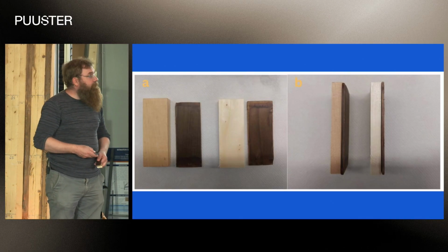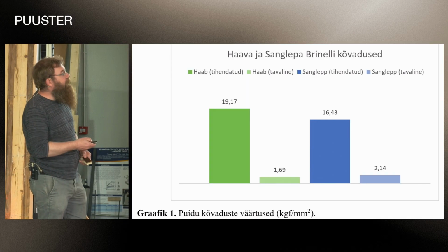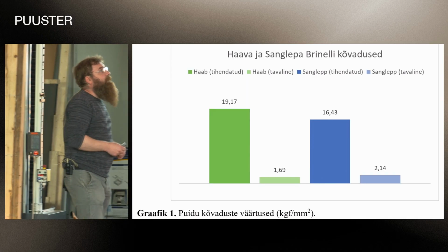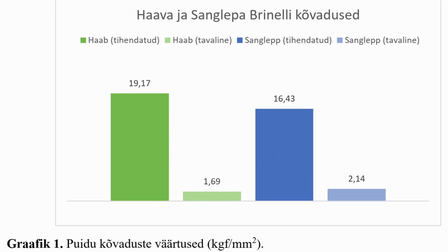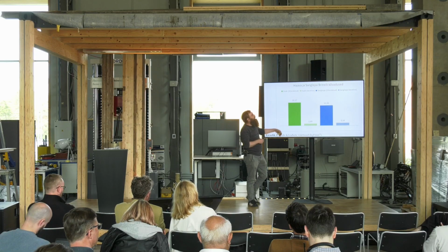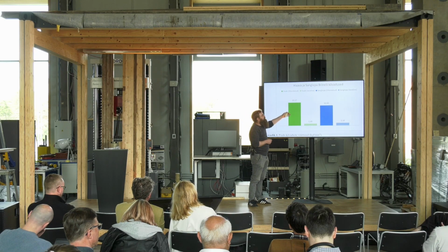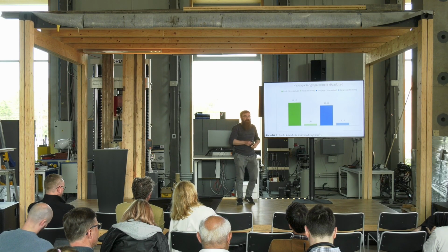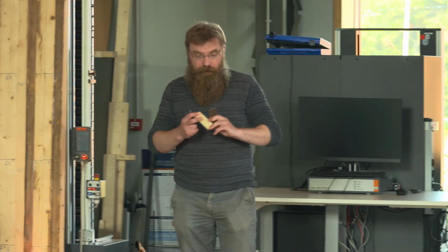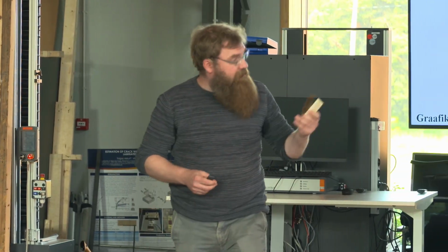But after densification, these are our samples here, we see that, for example, the Brinell hardness is increased quite drastically. We see here, this is untreated aspen, this is untreated alder, and then when we densified it, its Brinell hardness increased more than 10 times here for the aspen case. And here I have also now samples from this measurement.